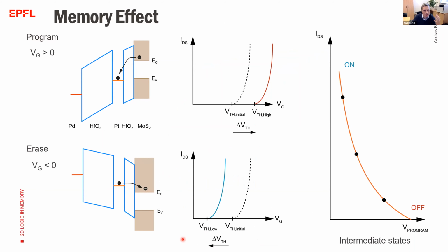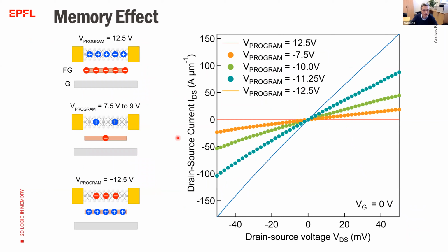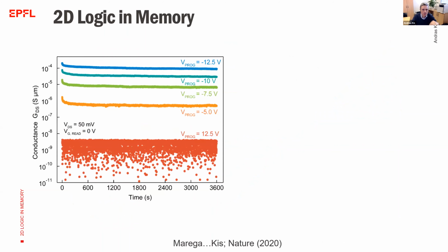But this can also be used in a more analog way. And instead of looking at this as a programming and erasing of memory, we can actually vary the amount of charges which is stored on this floating gate to program different conductivity levels into our device. So with this, we can use the memory effect both to store the data and to also program the transistor itself. And depending on the amount of charge stored on the floating gate, we can have a fully off transistor, a fully on transistor permanently, which memorizes the state, and we can also modulate the conductivity in between these two different states. And we can also do that much more precisely.